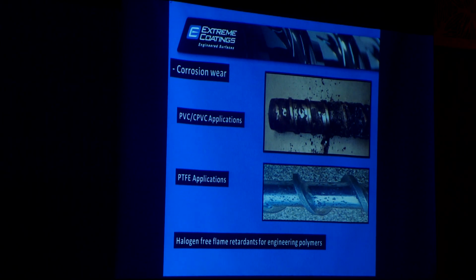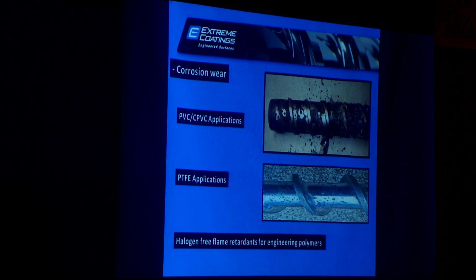The third kind of wear is corrosion wear. If you are processing PVC, CPVC kind of polymer, or let's say PTFE, where fluoric acid can attack your surface. Or even in some of the engineering polymers, we see HFFR, halogen-free flame retardant, you have to use. That itself is very corrosive in nature, which attacks your base metal and pitting starts happening. And that's how the wear happens. So this is the third kind of wear.